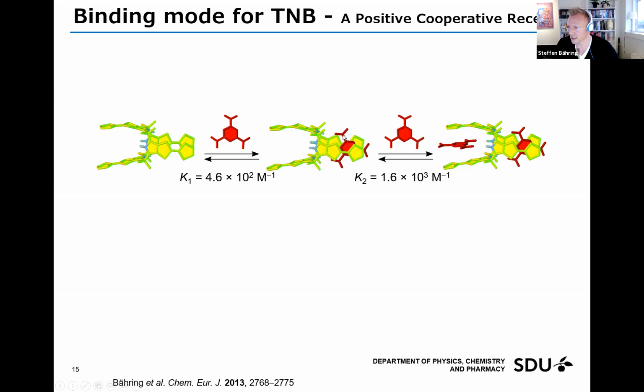And when the first TNB molecule is complexed by CT interactions, then it draws away electrons from the NH side. This makes the vacant NH protons more acidic, and therefore they will be better in forming hydrogen bonding interactions. At the same time, we have these hydrogen bondings here, and they again affect the electronics of the vacant TTF unit, making this a better electron donor. So overall, binding the first TNB actually makes the second binding much stronger, and you can see this is affected in the binding constants, where the second binding is actually quite a lot higher.